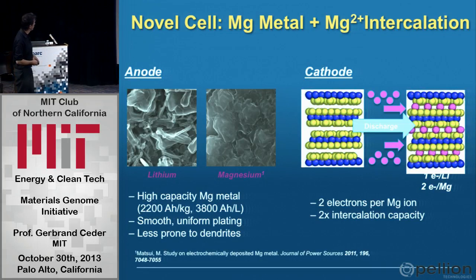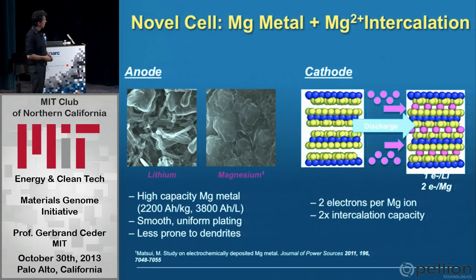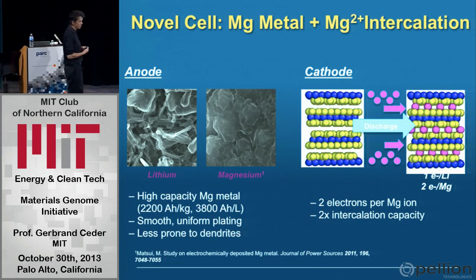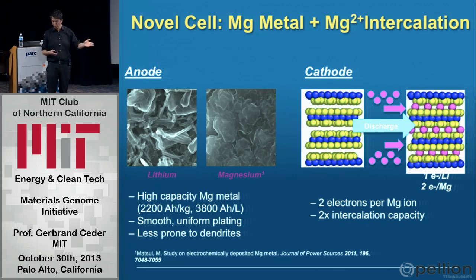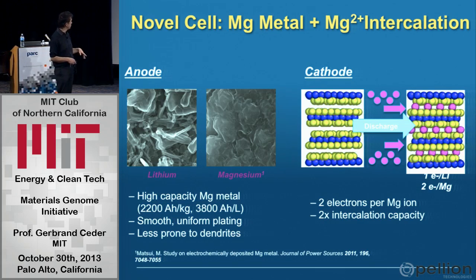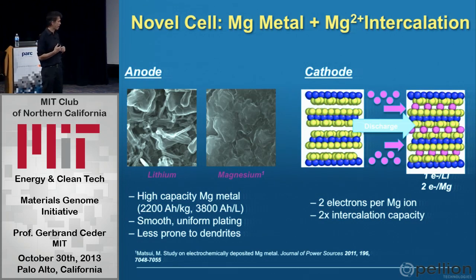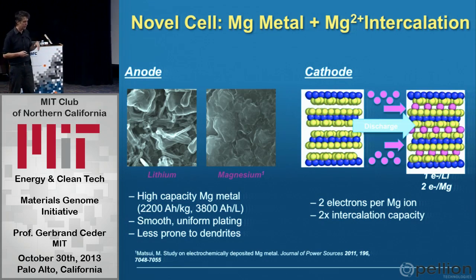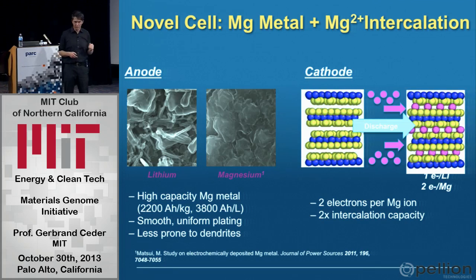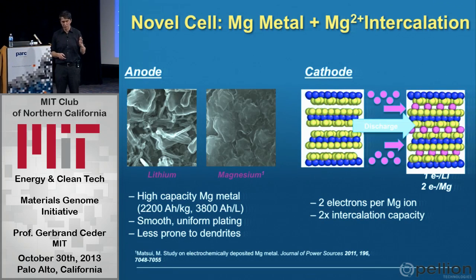Pellion was founded a few years ago and works on magnesium batteries. This is sort of the next step from lithium-ion batteries. In lithium-ion, you move a 1+ ion around, so you move essentially one charge per mass unit. With magnesium, you would move 2+ ions around, so at least in principle you can double the volumetric and gravimetric capacity. But it's actually better, because in lithium-ion you cannot use a metallic lithium anode as it's too dangerous. It tends to form dendrites when you replate the lithium. In magnesium, you actually can use a magnesium metal anode, and so you have an extremely energy-dense anode.